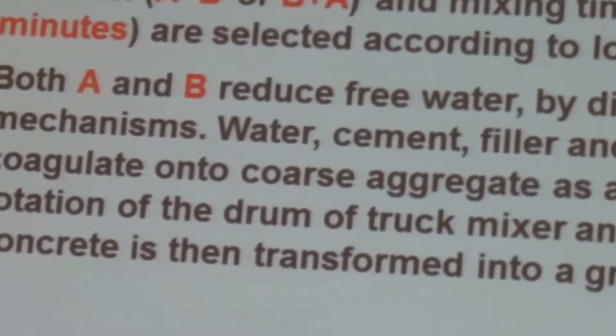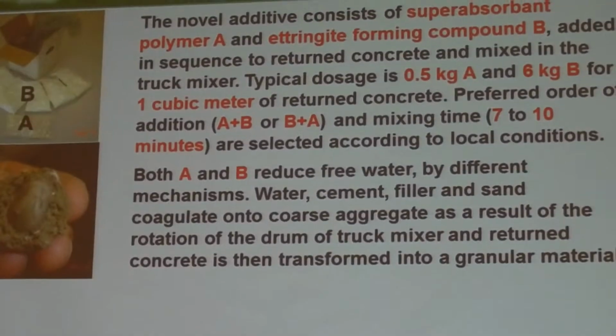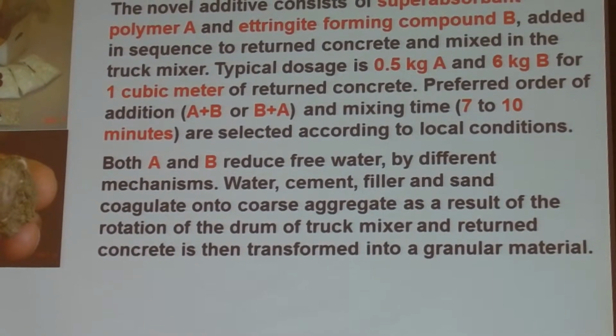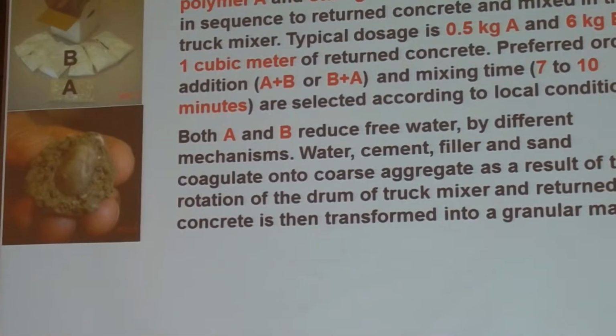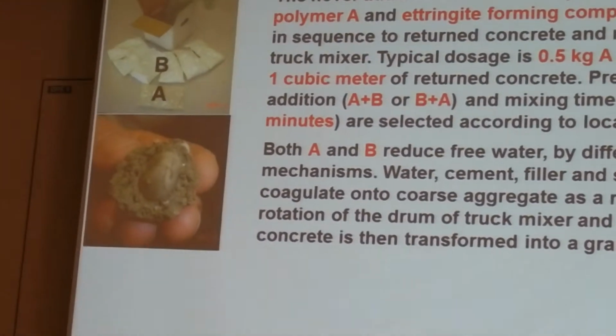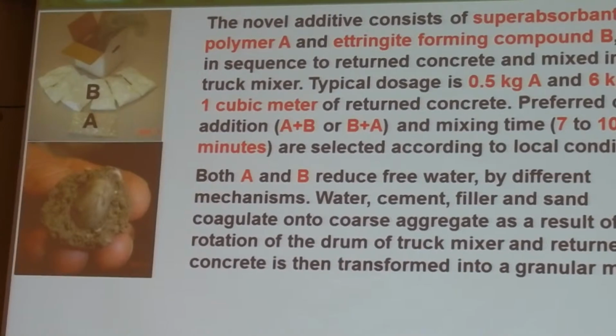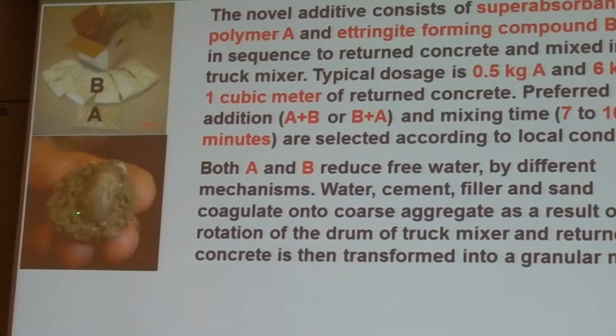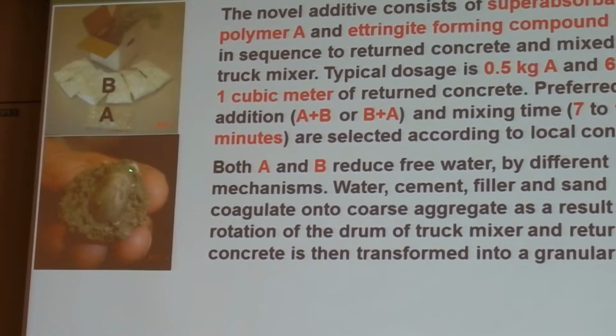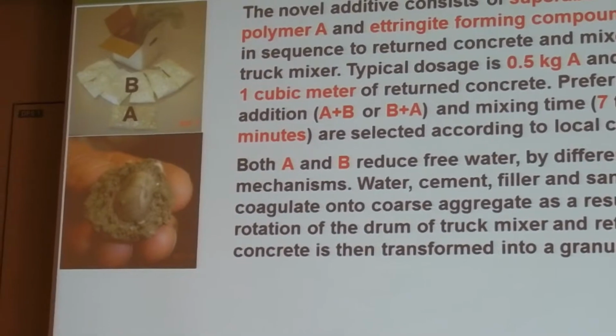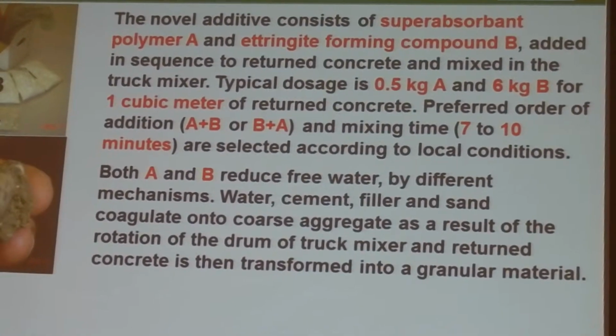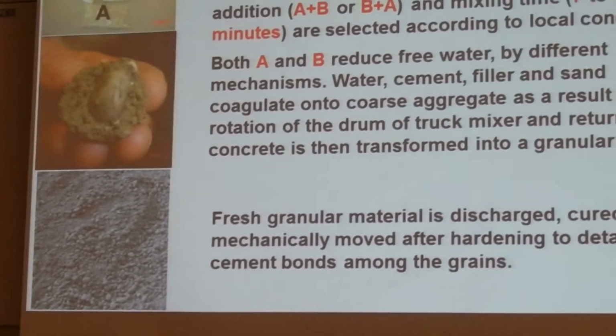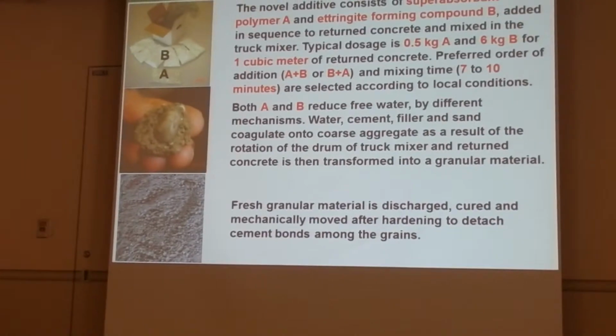Both component A and B act to reduce the free water. So they have the capability to absorb or consume free water, and they act by different mechanisms. And water, cement, the filler, all the fine particles of the concrete coagulate onto the coarse aggregate as a result of the rotation of the drum of the truck mixer. And consequently, the returned concrete is transformed in granular material, like this example. You see there is the coarse aggregate inside as a core, and around it there is all the fine material, including water and cement, coagulated on it.